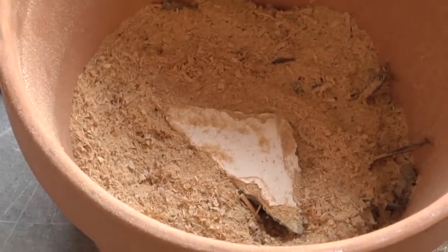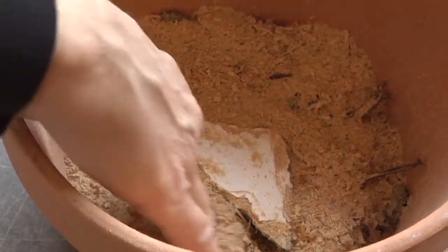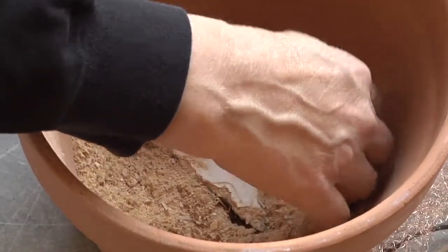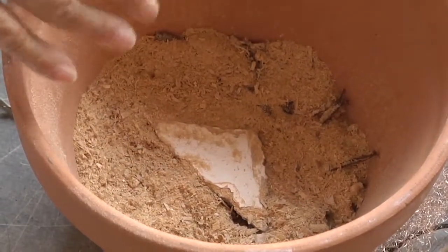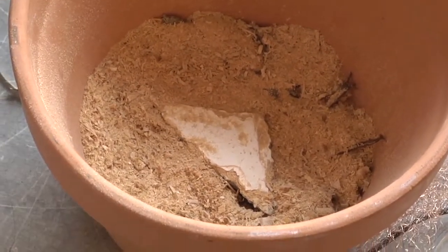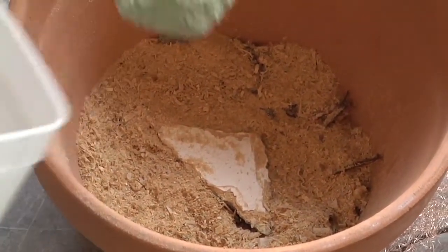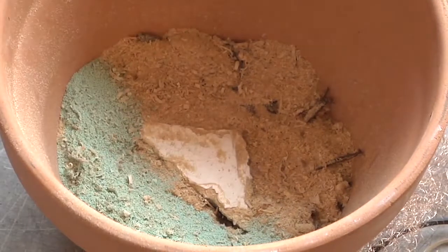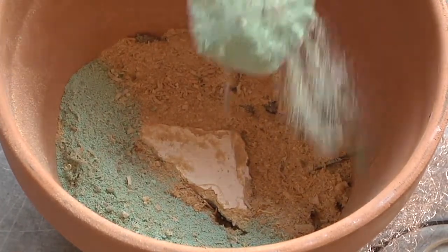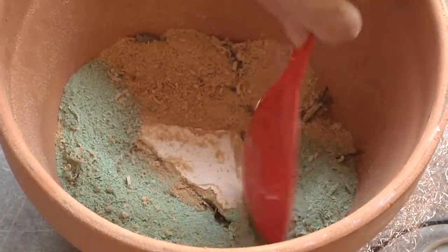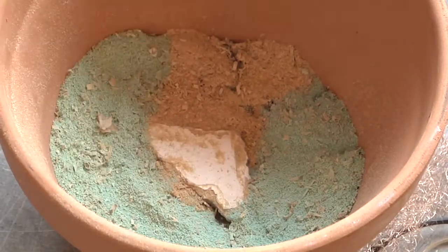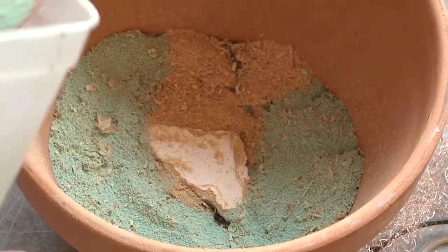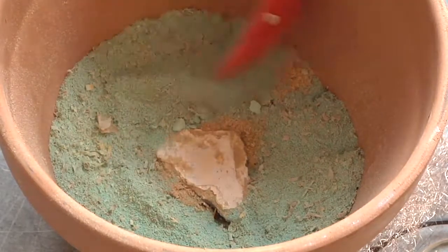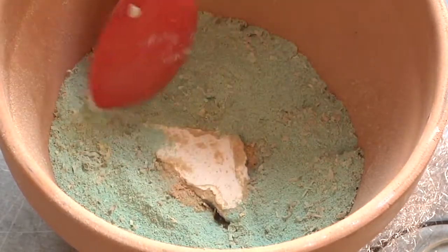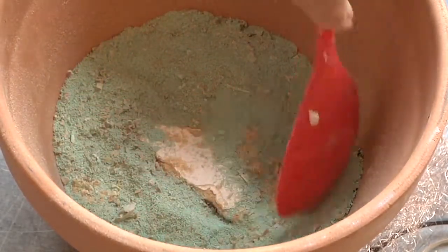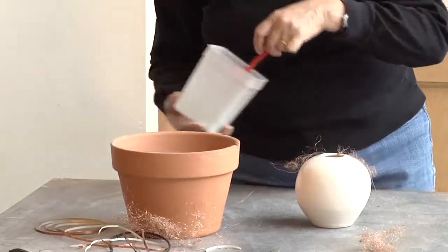Okay, so the kiln shelf is in there, and I have the wood chips and then the sawdust, and then I'm going to sprinkle some sawdust mixed with copper carbonate that has about 2/3 to 3/4 salt and 1/4 copper carbonate. And then about just some sawdust for kicks here. Should mix it up a little bit. Okay, and that should do it.